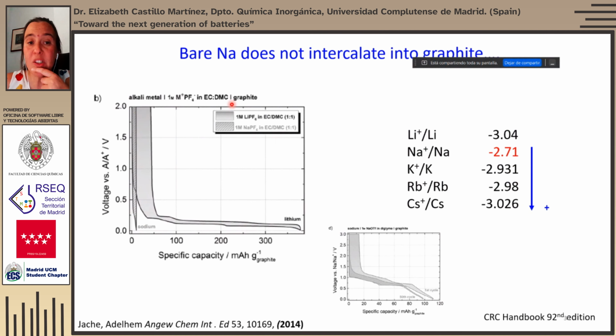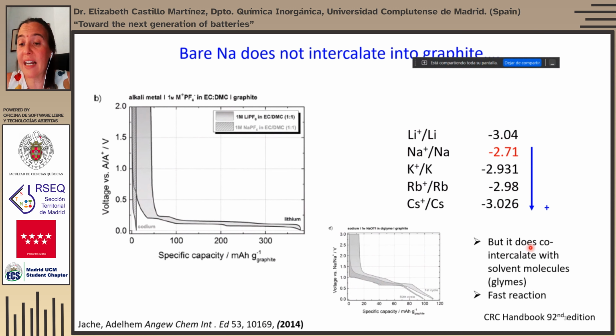However, it is possible to intercalate sodium ions co-intercalated with some solvent molecules at higher voltages, but as well at a lower capacity. But interestingly, this co-intercalation does occur at a relatively fast rate. The fact that graphite doesn't intercalate sodium ions has motivated lots of research to search for alternative anode materials.